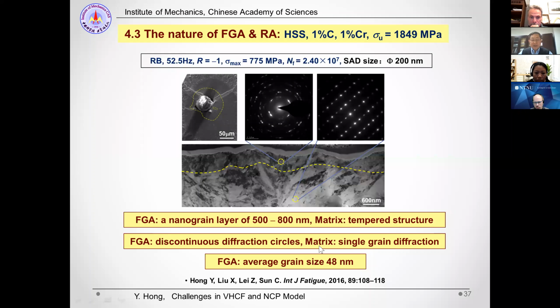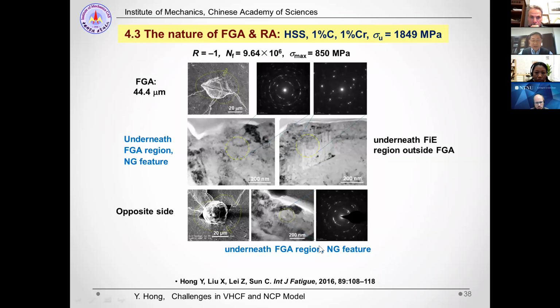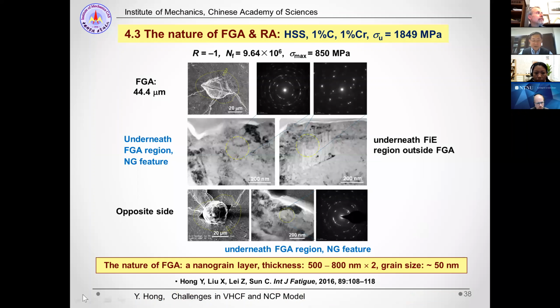nanometers. And we also use a specimen to observe both fracture surfaces and to reveal that both surfaces contain nanograin layer on the fracture surface. So we say that the nature of FGA in high-strength steel is a nanograin layer, and the thickness is between 500 and 800 nanometers, and the grain size is about 50 nanometers.